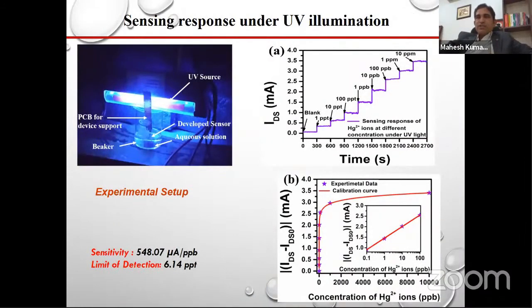Another thing, to improve the sensitivity further, we have used UV light, because in the water purifier we are using UV light to kill the bacteria. So we thought, can we put our sensor in front of this UV lamp, and see the effect on the sensitivity. So we used a UV lamp, and under it our sensor is there, and then we measured. We found our sensitivity increased around 600 times compared to without UV. We can improve the sensitivity by 600 times just by putting this sensor in front of the UV lamp.